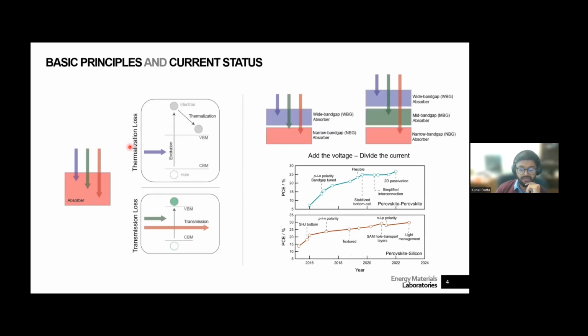To motivate why we need tandems, I think most of us know already, but just to brush up the fundamentals. If you look at a single junction solar cell, with light of different wavelengths coming in, what is a typical loss process? There are 2. The first is thermalization loss, wherein you hit it with light which has an energy higher than the optical band gap, and therefore you excite your carriers to a higher energy, and then they need to come back to the conduction band minimum. This energetic loss is your primary loss, and that's your thermalization loss. The next one is transmission loss, wherein the light is below the band gap, so it isn't absorbed, it's transmitted through, and you lose carriers in that way.